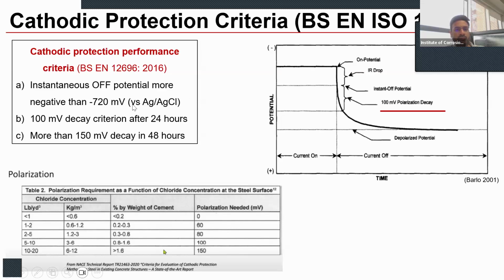If this instantaneous off potential is more negative than minus 720 millivolt, the system is working fine. Otherwise, we go and monitor the decay. In 24 hours, if we achieve the 100 millivolt decay, any of these criteria fulfilling the protection performance requirement is acceptable.